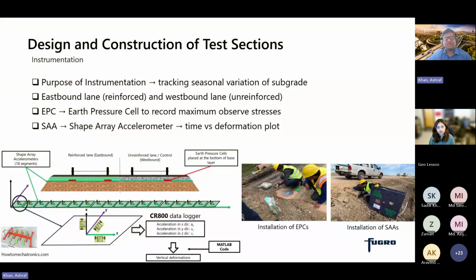And to monitor the performance, we actually did some instrumentation on the field. The purpose of the instrumentation was to track the seasonal variation of the subgrade, and we had the eastbound lane of the road as reinforced section, and the westbound was unreinforced section. If you look at the figure, we used both earth pressure cells, which were located at the bottom of the wheel path, at the bottom of the GRB layer as well. So the purpose was to get the maximum stress observed within this zone. Also, we have used shape array accelerometer. This is kind of a newer technique to measure the in-place movement of soil.